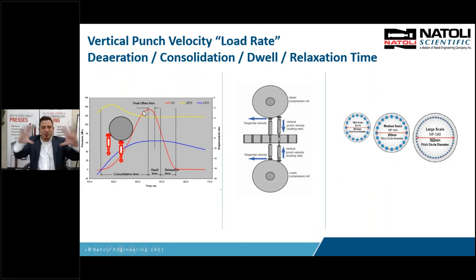That's a function of your compression roll diameter. So if you've got a large compression roller, you're going to have a longer consolidation time at a constant turret velocity versus a small compression roller that comes down and hits real fast. The dwell time is, some programs use 90% of peak to 90% on the unloading. This program uses peak to 80%, but the time is still the same. It's just where they shifted it. And that is a function, again, of the head flat of your punch and the turret velocity. And that's just a small portion of this whole event here. And then after we release the load, the relaxation time occurs. So this is one single compression event. The dwell time is a small area here. The consolidation time is a large portion of this compression event.